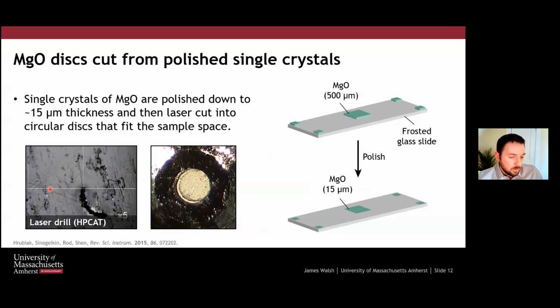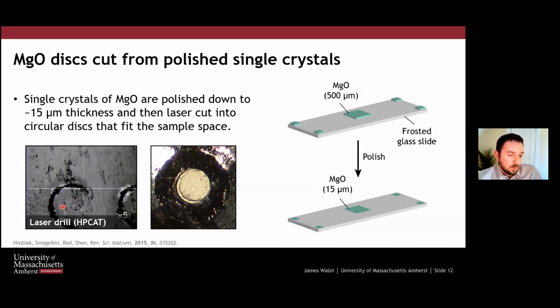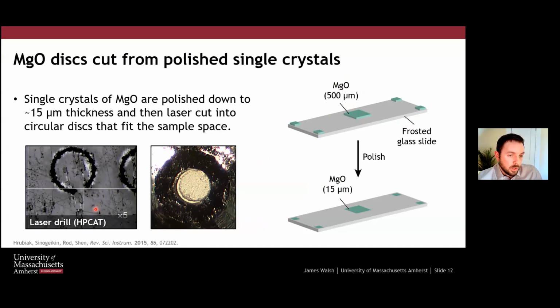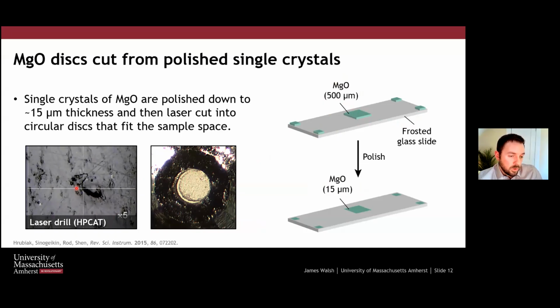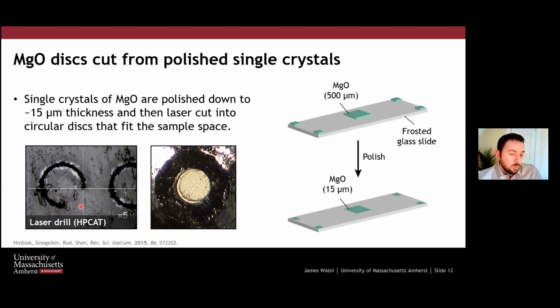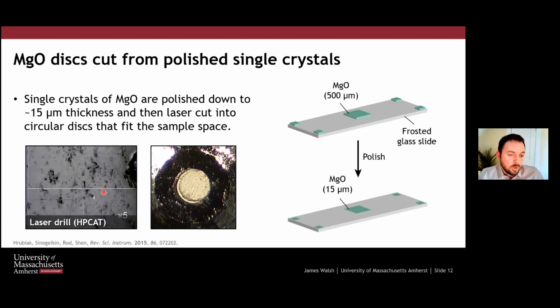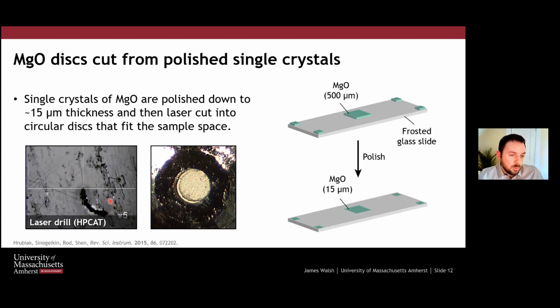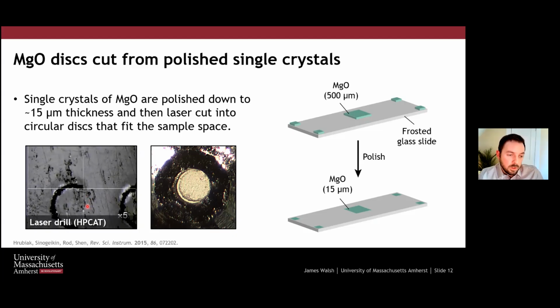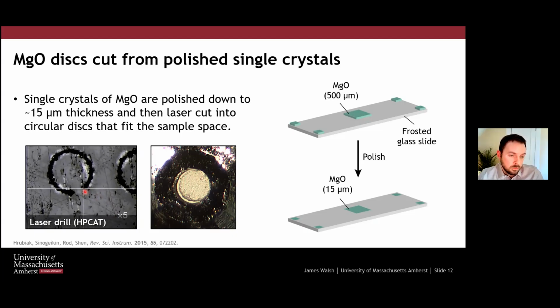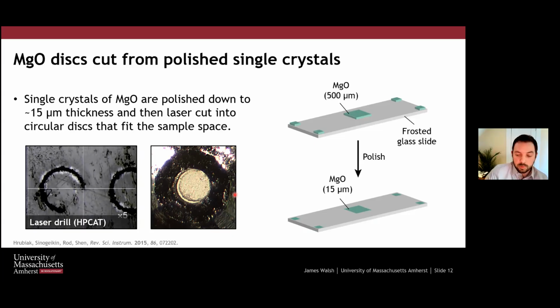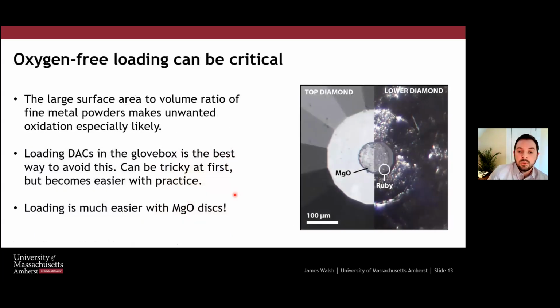And then we use the laser drill at HPCAT. This is the laser drill that Ross Rubiak put together. With this, we can machine out, basically by blasting away the MgO with this motorized stage, discs of MgO that are 15 microns thick with a total diameter of whatever we decide. We make that usually just a little bit less than the gasket sample space. And then we can take those and load our samples in this way.